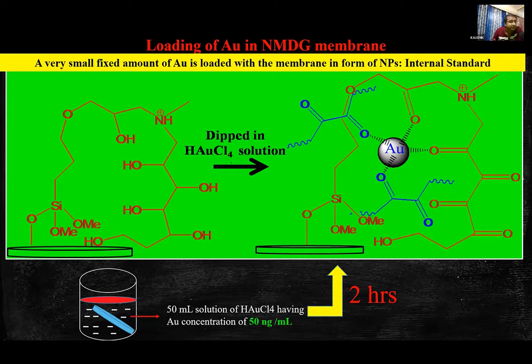In this work, I have developed a very novel way of introducing the internal standard. I took 50 ml of chloroauric acid solution in a beaker with a gold concentration of 50 ppb. In that solution, I dipped the quartz support having NMDG immobilized on it. After 2 hours, you can see that there are many hydroxyl groups present in the NMDG. These hydroxyl groups act as a reducing agent and reduce the gold present in +3 form to Au0, and this gold is absorbed on the NMDG membrane in the form of nanoparticles. So this gold will act like an internal standard.